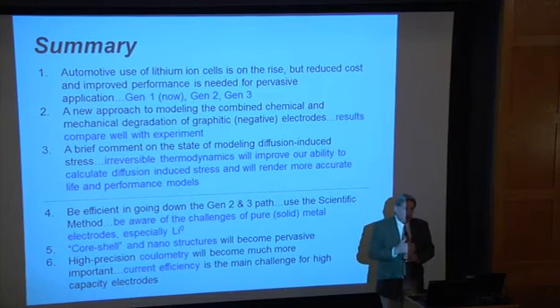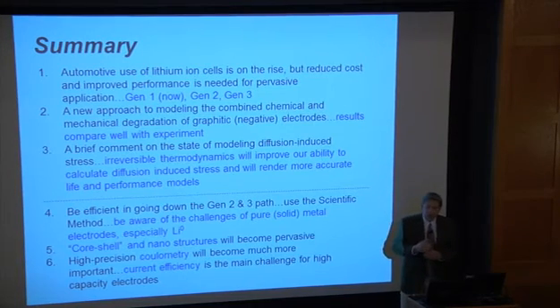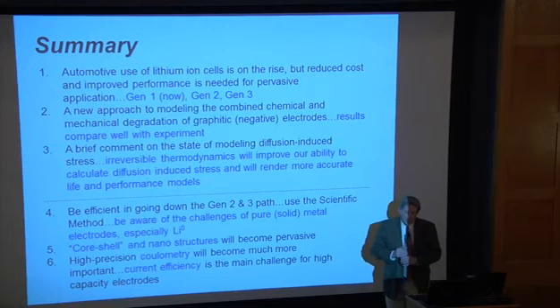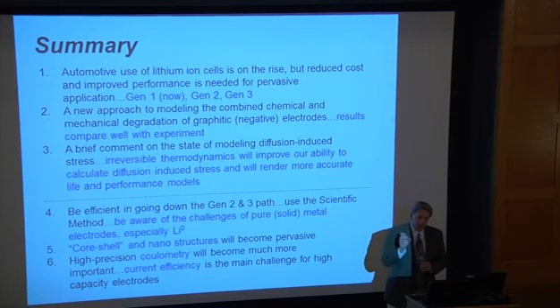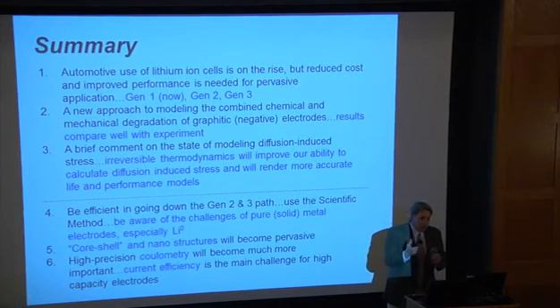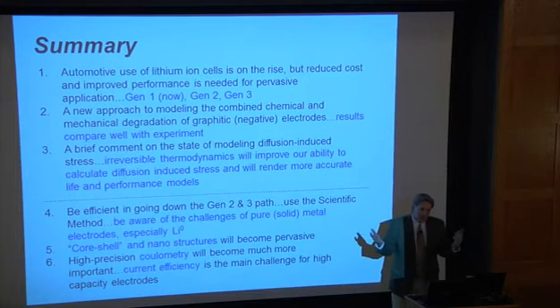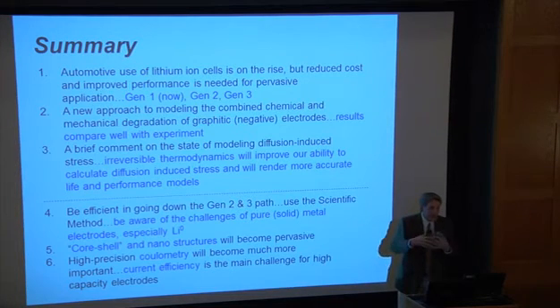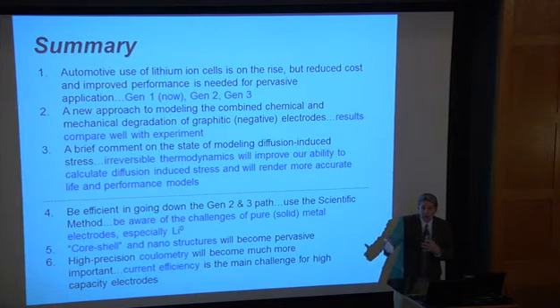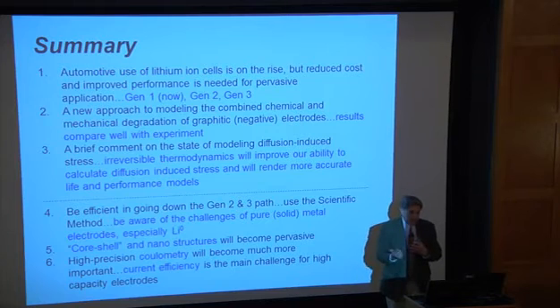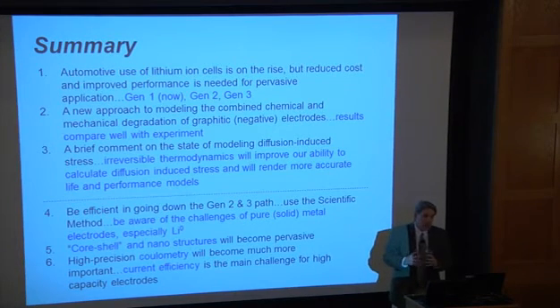But when you look at the early work by Cui at the Stanford group, they came out by stabilizing the mechanical decrepitation by going to small particles. Very small particles, when you get, say, 10 nanometers or so, the surface atoms start to dominate, and the particles tend to be more stable, and they mitigate some of the decrepitation problems. However, you exacerbate reaction with the electrolyte then, because you have high surface area. So what they did next was to go to this silica termination, which was quite promising.